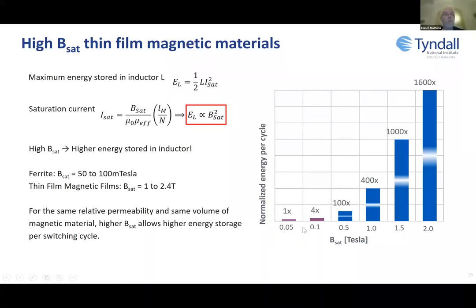And if you remember, what I said to you was ferrite can only operate in the 0.05 to 0.1 Tesla space. If you compare that against the thin film magnetic materials, which can operate in the 1 to 1.5 to 2 Tesla space, you can see that we could actually store far more energy in these thin film materials. Now, the thin film materials we'll use will be very thin compared with the thick ferrite materials, but it shows why they are a useful material.